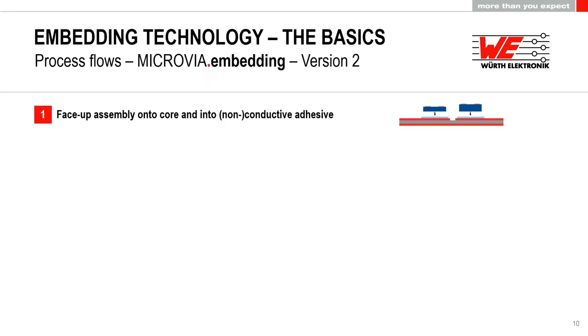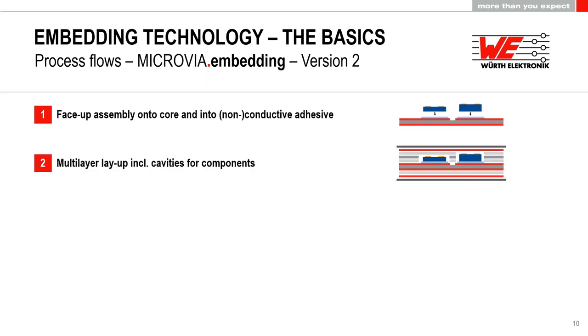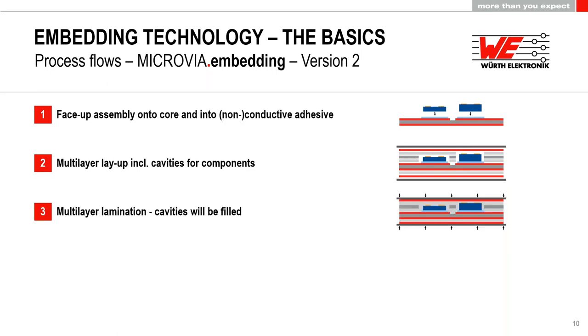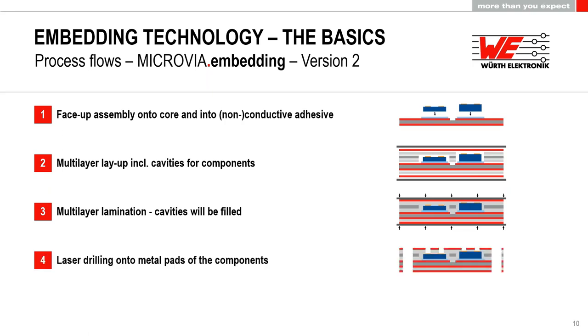Here we could use a standard backside metal like silver or something like this and connect it to the pre-structured core already. Then, as in version one, we go to the multi-layer layup. We create these cavities so that the components are not being destroyed in the first part of the pressing process. Then we heat up the whole system, we put pressure on it, and the resin starts to flow around the components so that this is being done during embedding. And again, we go to the laser process and we drill the microvias directly onto the copper pad or onto the pads of the components.